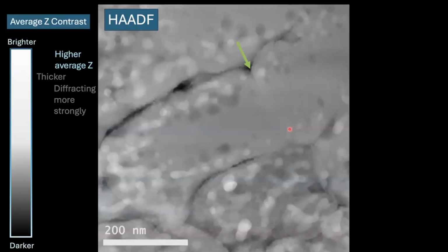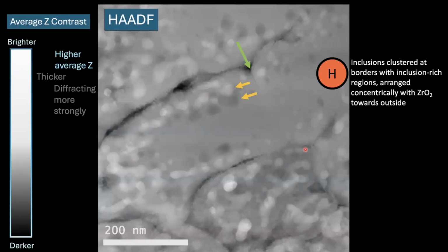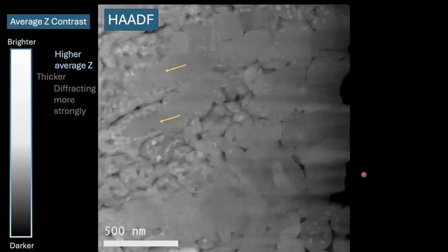But I do want to talk about this. Here's one of those really tight granule boundaries, and here are some inclusions that are around the edge. So there are a lot of inclusions that are clustered at the borders of granules. They're at the borders of granules that touch inclusion-rich regions, and they're arranged concentrically with zirconia towards the outside. So here's a bigger picture of that.